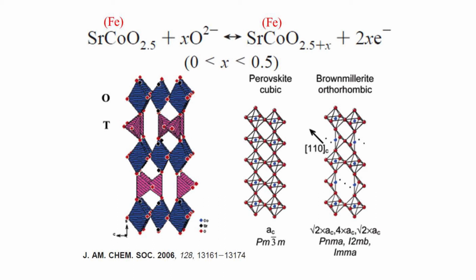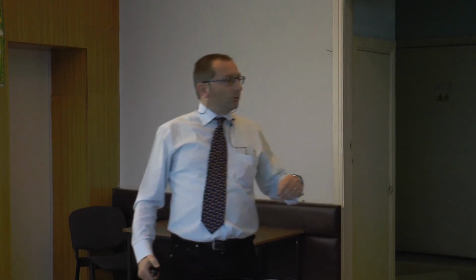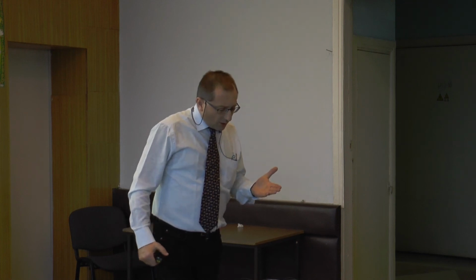Now, of course, we want to investigate how it is possible to move from oxygen 2.5 to oxygen 3. As we are dealing with crystalline material, we will run diffraction, but not X-ray diffraction, but neutron diffraction, because the element we are interested in is oxygen. And oxygen has a very low X-ray scattering power with respect to the heavy cobalt and even heavier strontium. So the same experiment done with X-rays would lead to much less contrast in what we are looking for. So the technique of choice in this case is neutron powder diffraction, because we are dealing with powdered materials.